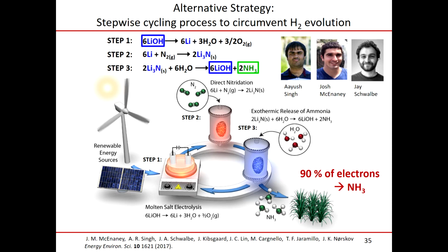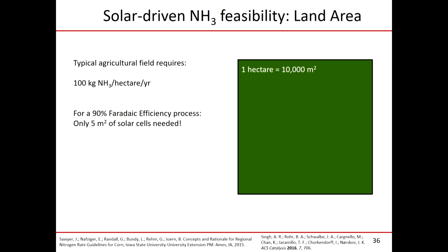It's not a catalytic process. It's a cyclic process where if you give me inexpensive renewable electricity, we can plate lithium from lithium hydroxide in a molten salt. And then that lithium metal, you just expose it to N2. It'll form a nitride very readily thermodynamically. You take that lithium nitride, you dunk it in water, it'll hydrolyze, and you end up making ammonia and lithium hydroxide, which you can cycle right back and replate. You can just keep going over and over and over. So we've demonstrated this process works where 90% of the electrons are actually going to make NH3. That's a very high selectivity.